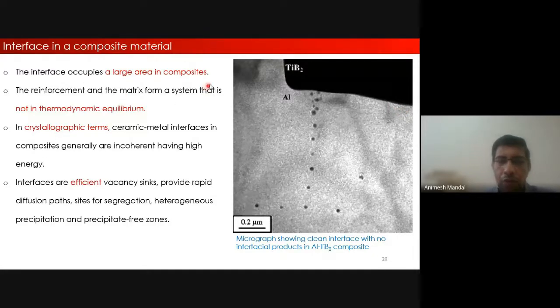Why focus should be laid on the interface is that it occupies a large area in your composites. And again, just to reiterate the point, it becomes more important especially when you're dealing with metal matrix composites and ceramic matrix composites, because the processing temperatures are quite high, right? At those high processing temperatures, there are chances that you may end up having some reaction products at the interface. It may not be that significant when you're dealing with room temperature processing, or very, very low temperature processing. But in metals, all the processing is generally done at relatively high temperature. So that's why characterizing the interface becomes very, very important.